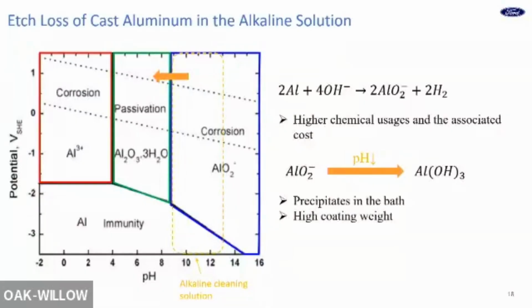Now, just to summarize the etch loss and the pretreatment on the cast aluminum. We do see a high etch loss in the cast aluminum, and we see selective dissolution of aluminum, which forms a porous silicon-rich structure. This structure has a very high surface area, and it can allow more zirconium formation, so you can see a higher coating weight. So with this high etching and the higher coating weight, you may see higher chemical usage or higher cost.